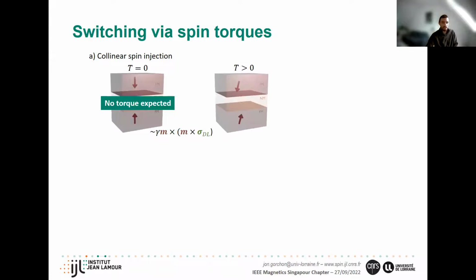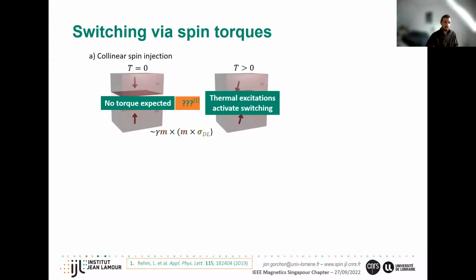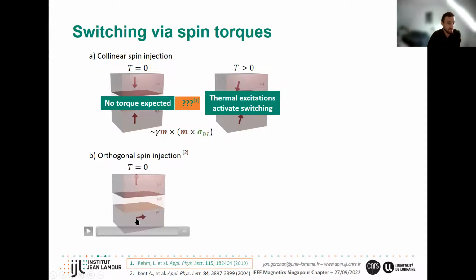Now, in practice, you always have some temperature, which induces some small thermal activation. This induces some small angles, and so you can build up a torque. So we say that at finite temperature, we have thermal excitations that activate the switching. There's some lag related to this, but you can switch. Now, it is not totally certain that you have no torque at zero temperature, because there have been some recent experiments at very low temperature where they could switch very quickly in this configuration. So there's some interesting physics still to be understood here. But if you want to go fast, the easiest solution is to go into the orthogonal configuration. Here you put one of the ferromagnets transverse to the other one.